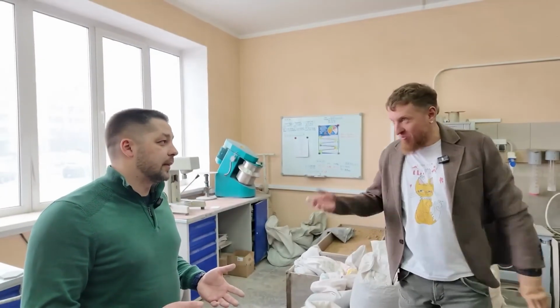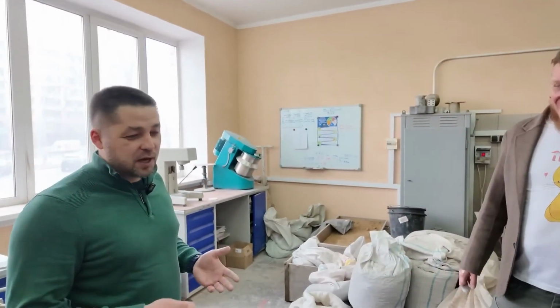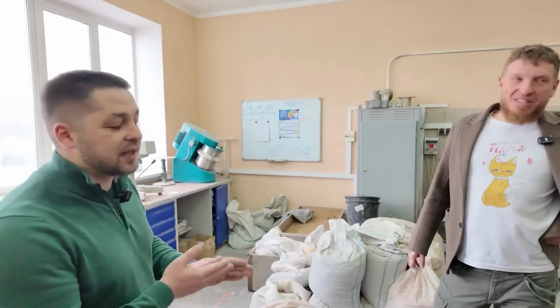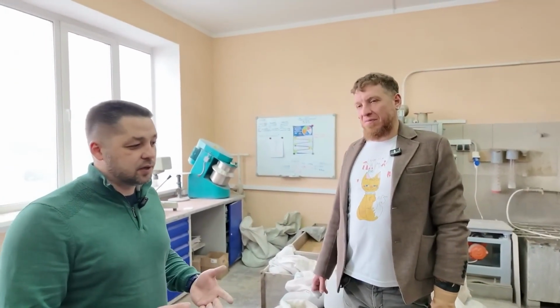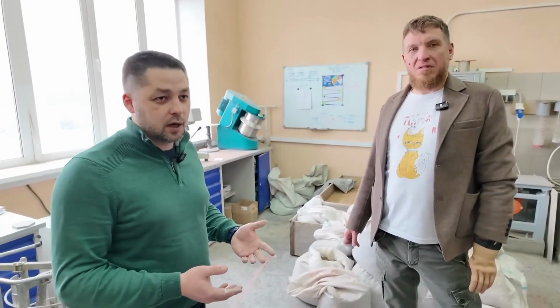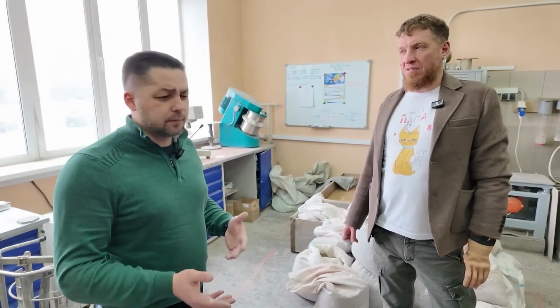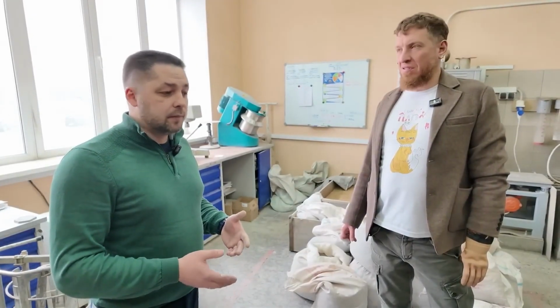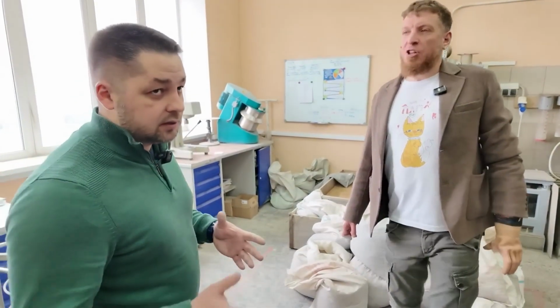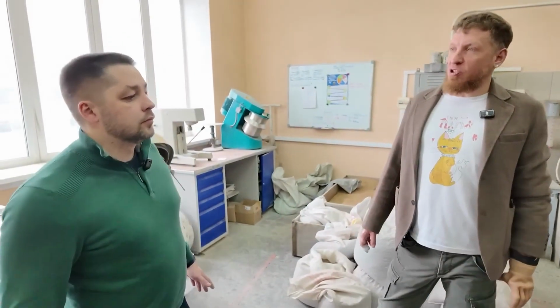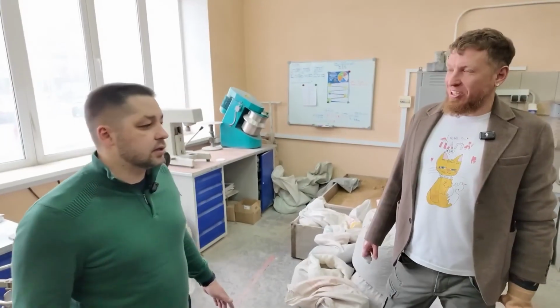You just need to, as an example, use an air entraining additive. You don't need extra strong concrete. Class B35 or B40 is enough, and you can buy or mix it. Add the additive in the right amount, measure the air content once, and you're done. You can then just interpolate by density. It won't fall apart, you just need to do it, that's all.